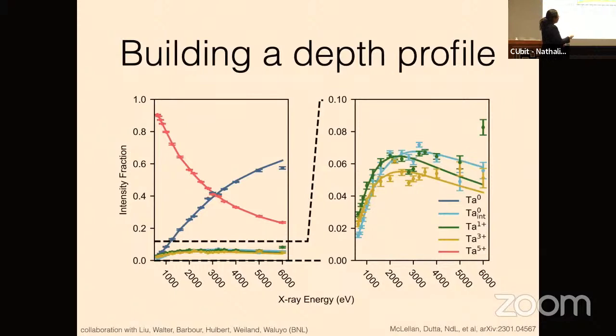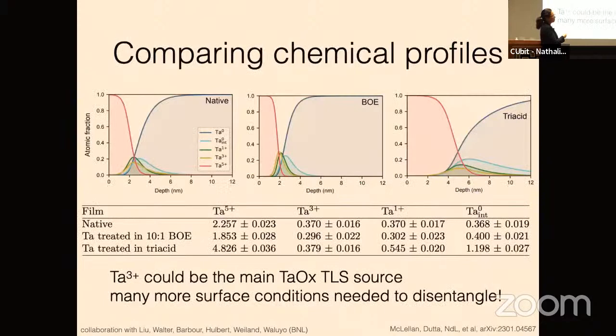And then now we can take all of this data and use that to actually generate a depth profile. So we can basically put in trial functions to figure out where all of these species are, and then look at the comparisons between the native oxide, this BOE dipped sample, and the triacid sample. And okay, there are a few things that we can extract from this, like just the total amount of each of these species, but we can also look at things like their total distribution throughout this layer.